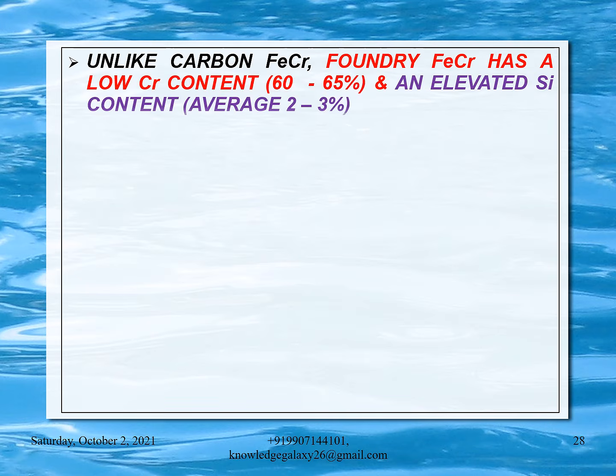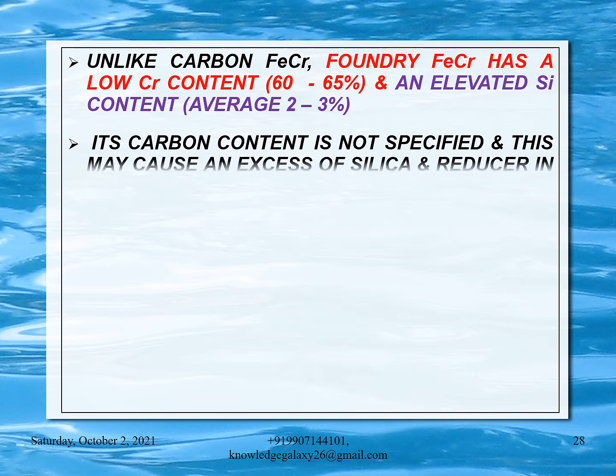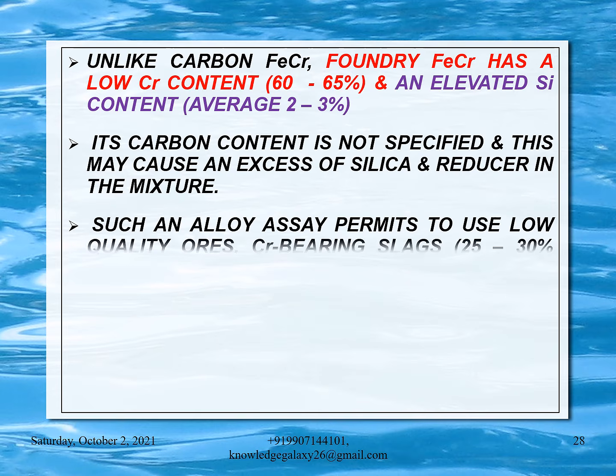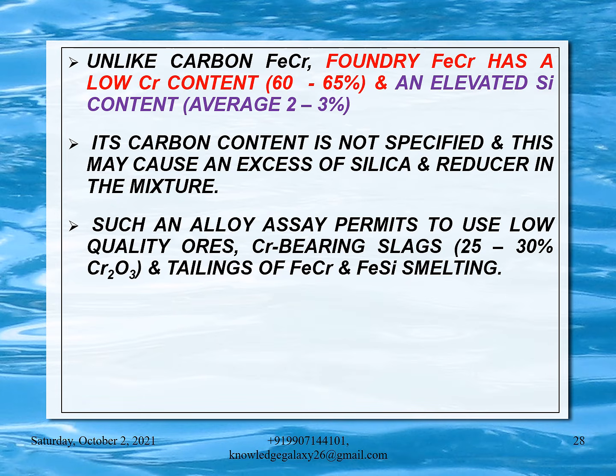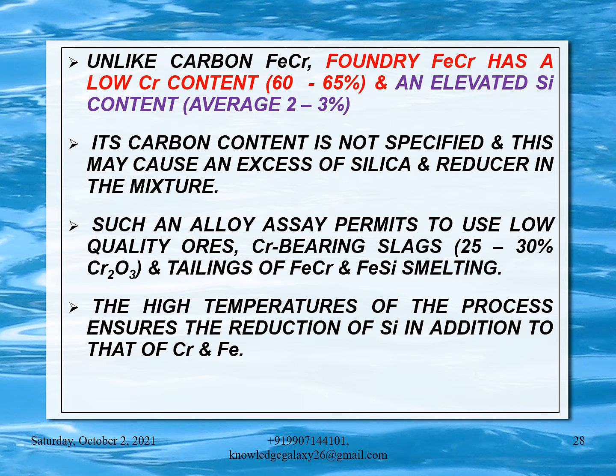Unlike carbon ferrochrome, foundry ferrochrome has a low chromium content, that is 60 to 65%, and an elevated silicon content which averages 2 to 3%. Its carbon content is not specified and this may cause an excess of silica and reducer in the mixture. Such an alloy assay permits the use of low quality ores, chromium bearing slags with 25 to 30% Cr2O3, and tailings of ferrochrome and ferrosilicon smelting. The high temperatures of the process ensure the reduction of silicon in addition to that of chromium and iron.